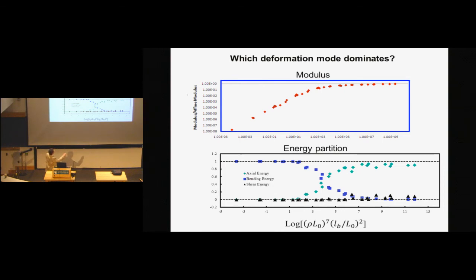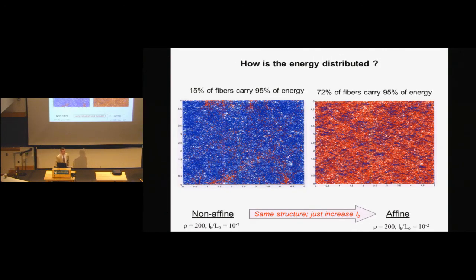So you see what happens. At about the point where you shift from the non-affine to the affine, the energy is also shifting from the bending to the axial. Okay? Which means that if I'm in the affine range, I'm storing energy mostly in the axial, while if I'm in the non-affine range, I'm storing energy mostly in the bending. Okay? So it pretty much tells me how these fibers store energy, not how they deform, because I really don't know what type of load I apply on the scale of a single fiber, but how the energy is being stored. That may or may not tell you much, but I hope this one will tell you something.